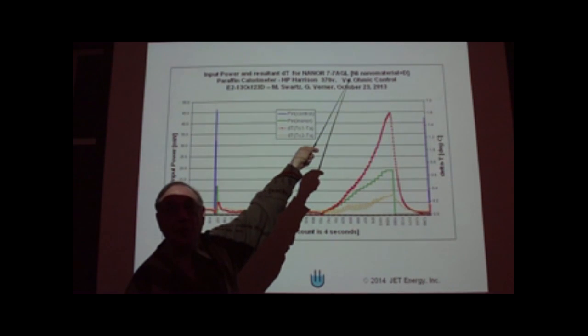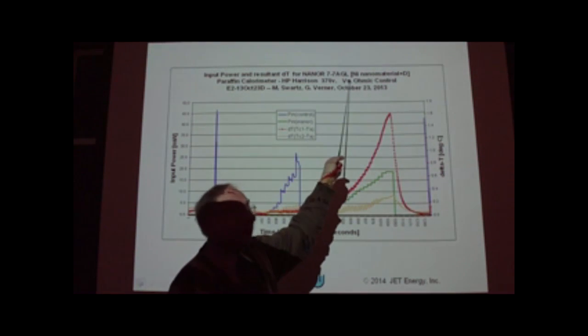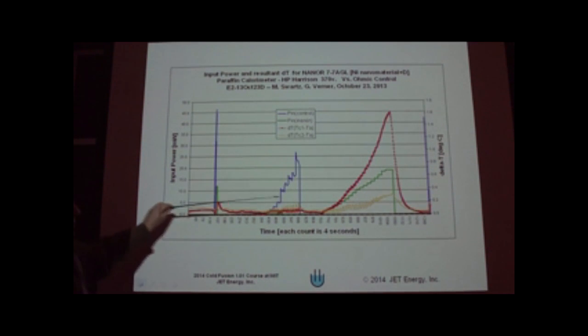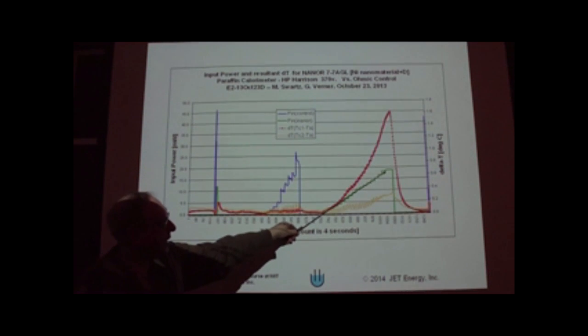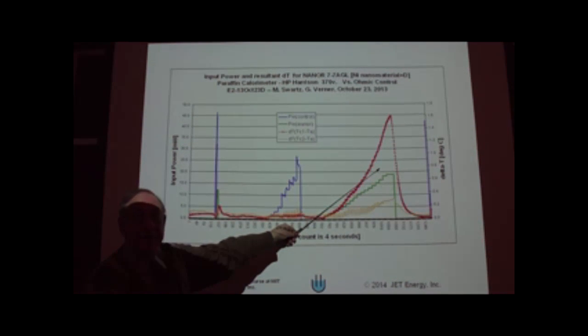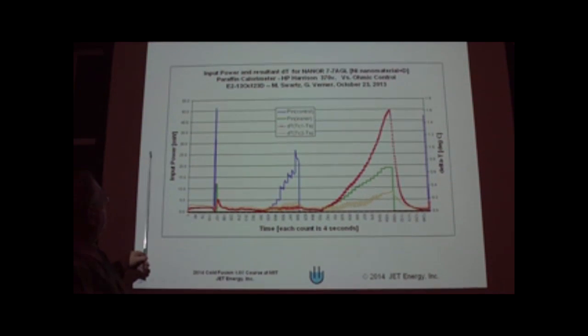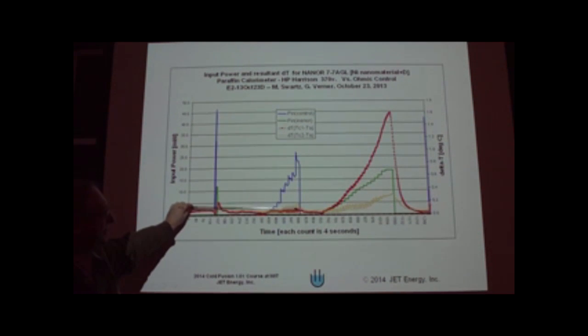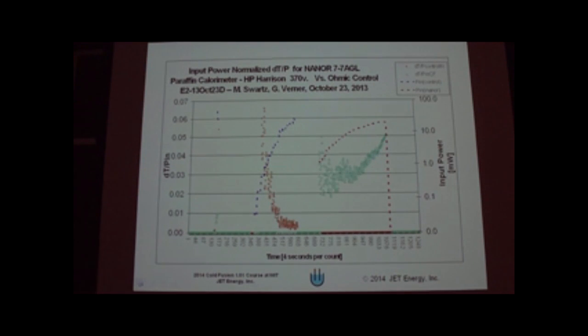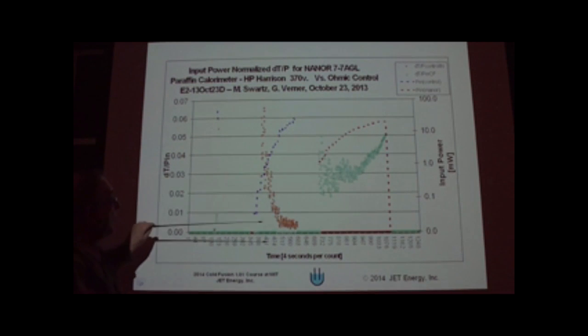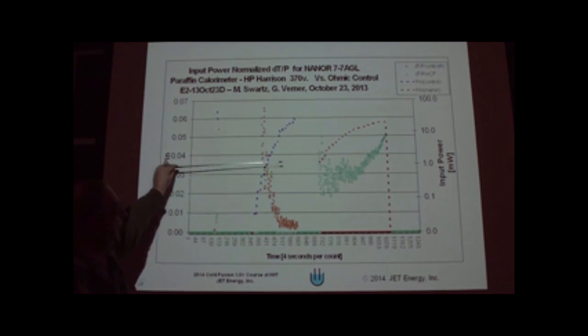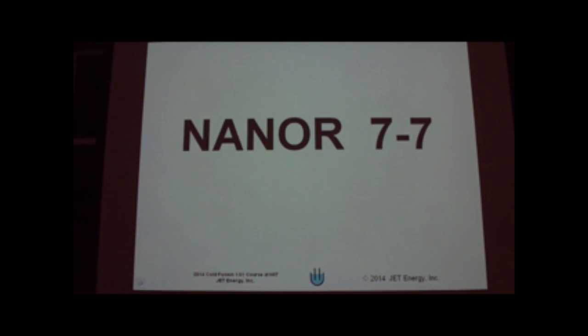Okay, 7.7. Here's another one where I think this one is solely nickel. There's no palladium in this. This is pure nickel nanomaterial loaded with D. Here are our calibration pulses, our ohmic control, input to the NANOR, which again is nickel with D, and this is just delta T. When we normalize the delta T by the input power, we can take the ratio. So we match the impedances here to here, and that's our ratio.